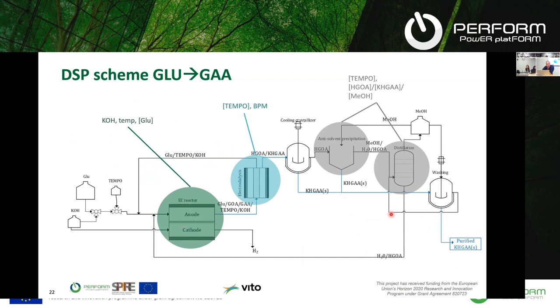And this is how a DSP scheme, together with the reactor, of course, would look like. So in this case, this is the electrocatalytic reactor where glucose is reacted with the TEMPO in alkaline conditions and is oxidized to gluconic acid and glucaric acid. This goes into an electrodialysis, so the 3 compartments set up with bipolar membranes, and we get on one hand